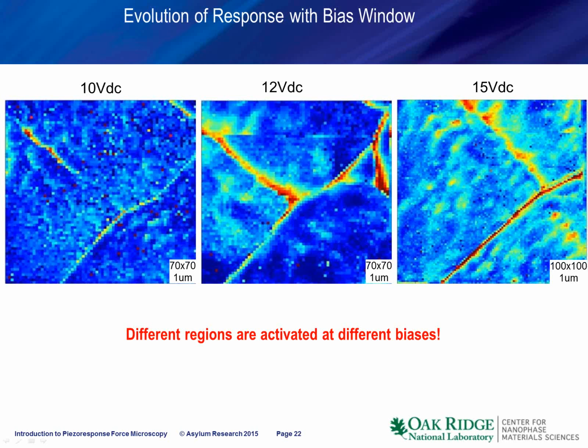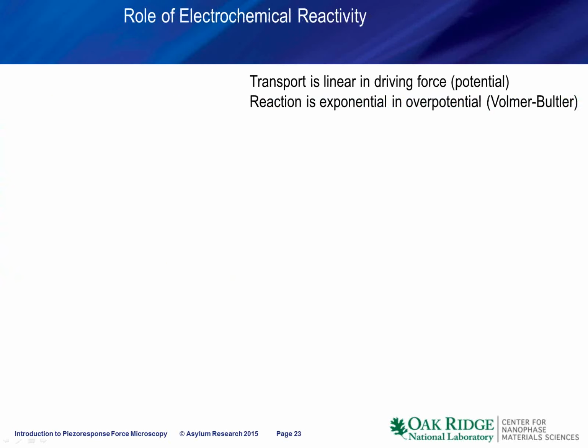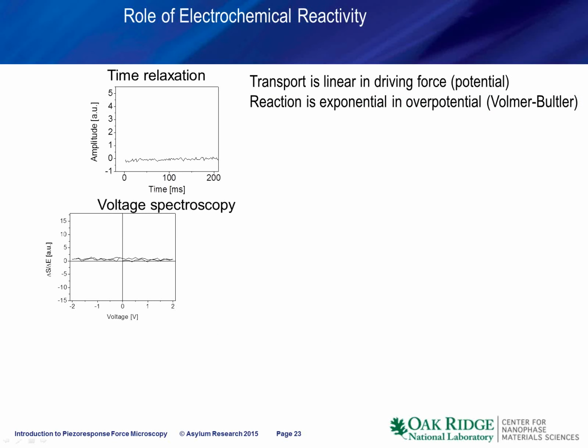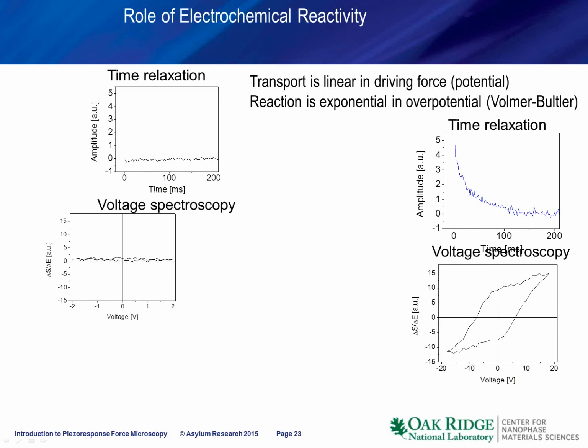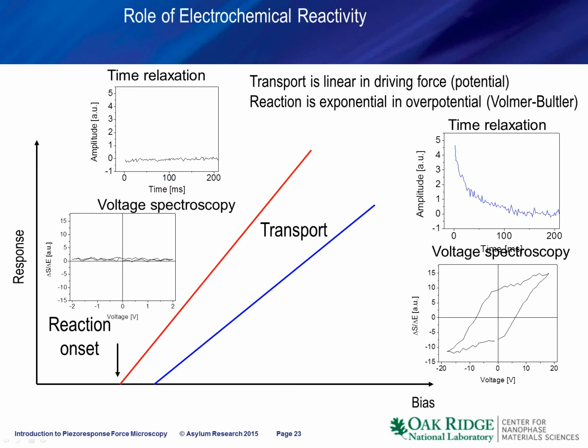So why is it happening? The reason simply deals with the fact that transport is generally linear in driving force, and reaction is exponential in the driving force. So in this case, for low biases, the process is limited by the reaction. At high bias, the process is controlled by the transport. What we see is that for low biases, there is no hysteresis loop and no time relaxation. For high bias, there is a time relaxation and a hysteresis loop opening. We can visualize this dependence schematically as this red and blue curve. So the onset of reaction and the slope can be different in different locations.